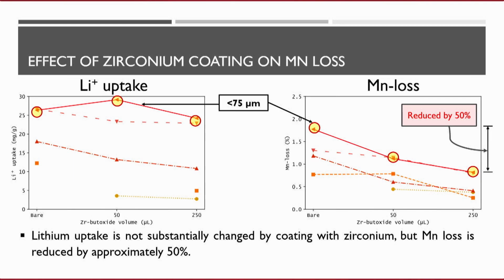One of the most promising, just to finish up here, is coating it. We're doing coating and doping, which is what we're funded to do right now. So we put a thin veneer, in this case of zirconium, on the outside that's porous. It allows lithium and protons in, but hopefully will inhibit the loss of manganese.